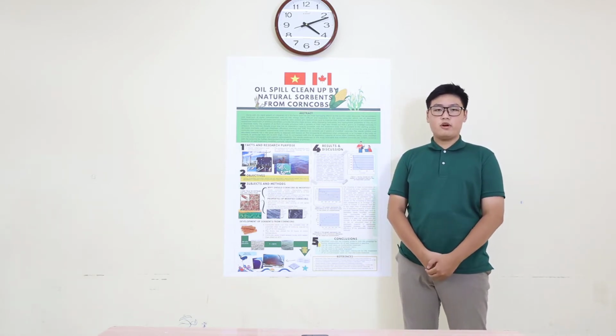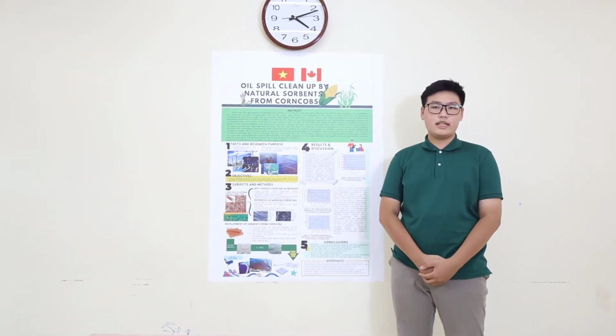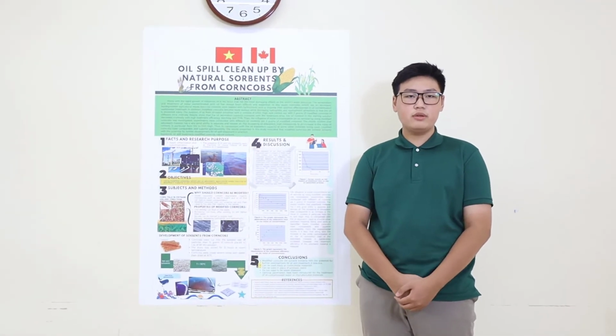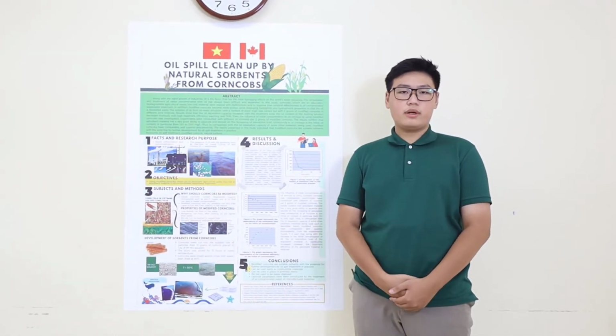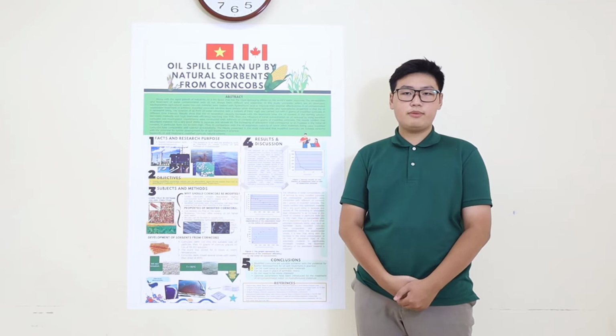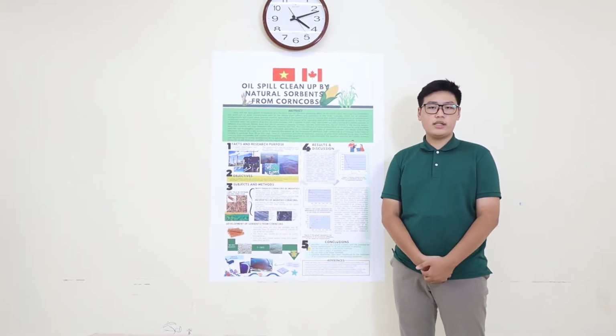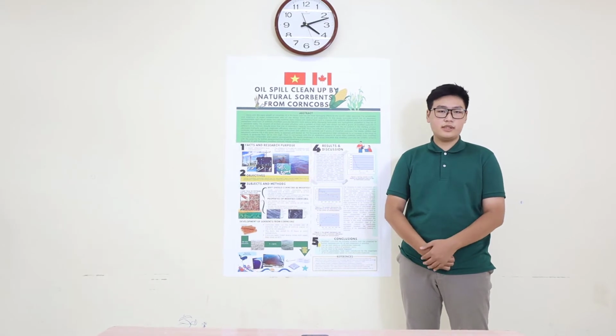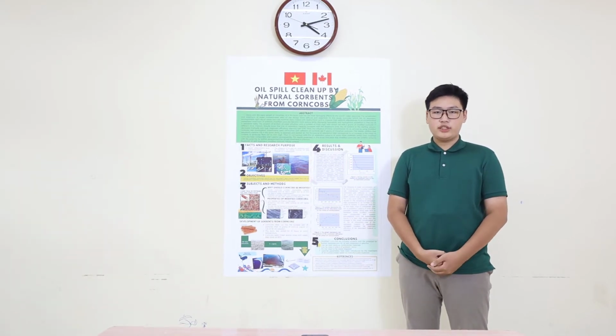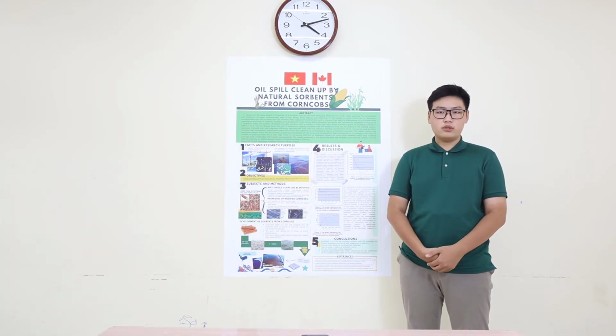The sorption of oil from an oil-water emulsion with a content of 2000 mg per liter was carried out with 2 grams of modified corn cob at different time intervals. The results in Fig 1 show that the oil separation capacity increased with the treatment time. When equilibrium is reached, the oil content in the static solution decreased markedly, with treatment efficiency reaching over 70%.